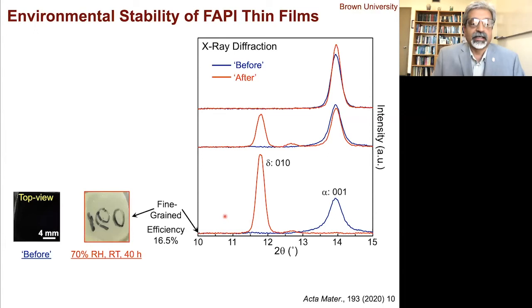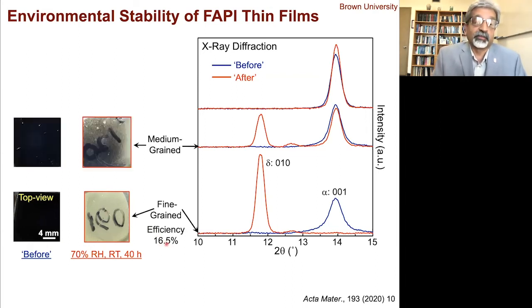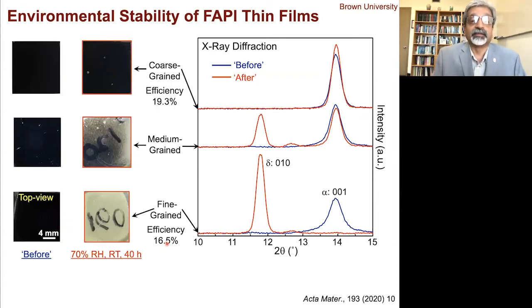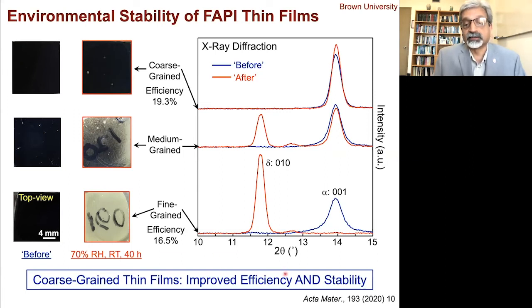So now let's look at the performance. This is fine grain, and this is the X-ray diffraction pattern, which basically shows this is before. Of course, it's black because solar cell materials are black. They absorb light. But when you treat this with a sort of severe treatment, 70% relative humidity at room temperature, 40 hours, this film is transformed to delta. It becomes transparent. You can read what's behind the thin film. And the efficiency of these solar cells is about 16% at 70%. Medium is somewhere in the middle, but when you have these coarse grain materials, the efficiency has jumped to 19%. And after this, you still see that the film is actually black. So now what we have done here in coarse grain thin films is not only improved efficiency, but also stability in these perovskite solar cells.